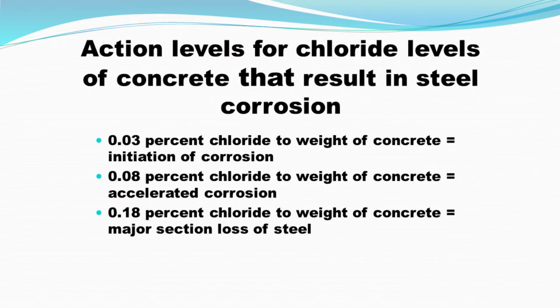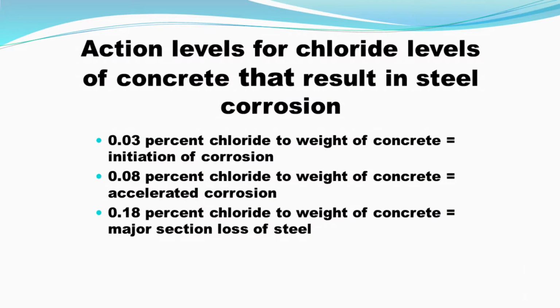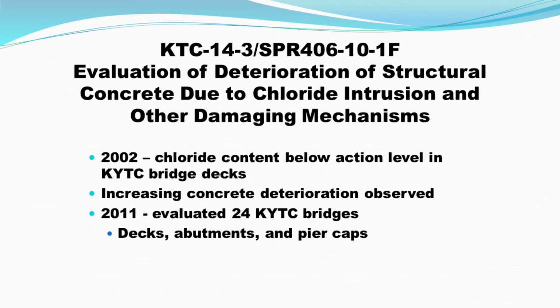Although there are a number of ways to quantify action levels for chlorides or salts in concrete, for the purpose of the presentation we've chosen what we believe to be the most regularly referenced values. That would be 0.03 weight percent, or percent chloride to weight of concrete, which is enough to initiate corrosion of steel reinforcement. At 0.08% chloride, you get accelerated corrosion of the reinforcement, and at or above 0.18%, you have a major section loss of the reinforcement.